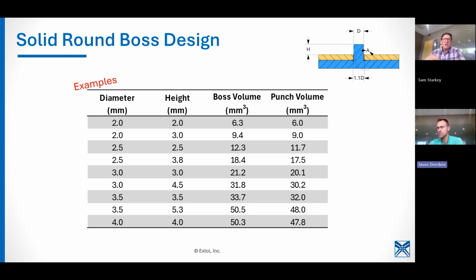So we're either going too deep and we're curling the material up around the tip where it doesn't like to release. We like to keep all of that material in the cavity. So there's possibly some design limitations there where you might be potentially undersized in volume on the punch. The other thing is with sticky materials, like we talked about with PBTs and things like that, we could be processing too hot, and then you could be getting some sticking. And once it starts sticking, it gets much worse, much faster.